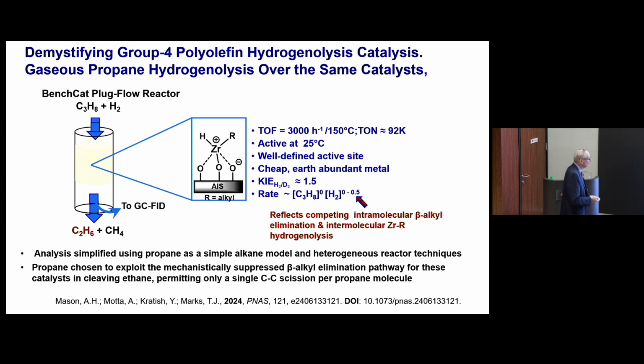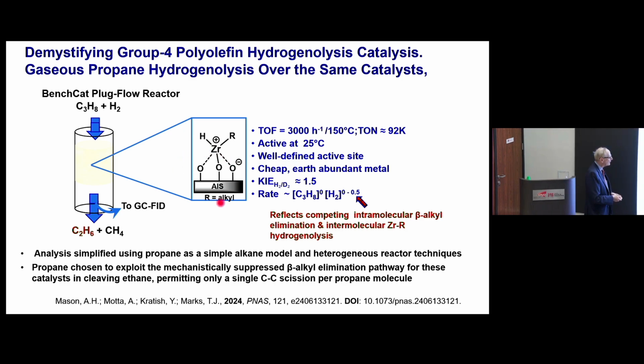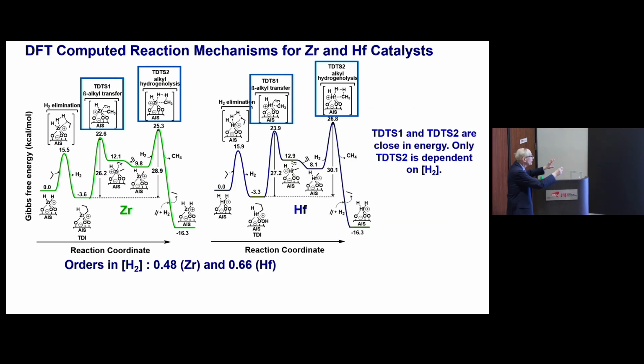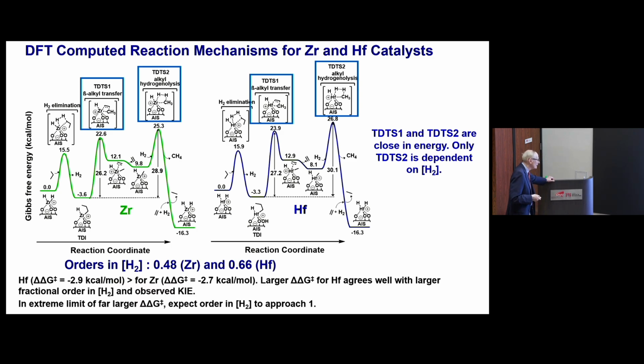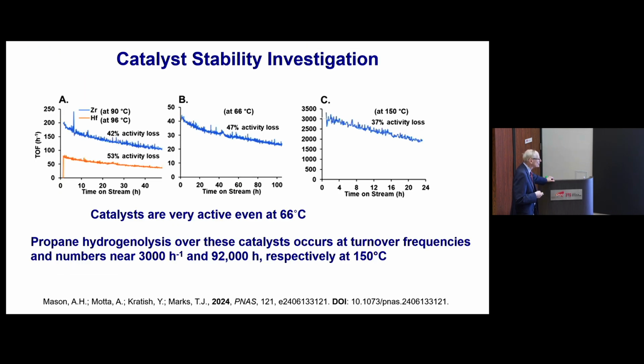And so, for example, the rate law is this weird thing that varies with the hydrogen pressure. And it turns out to be a very simple explanation. And I won't go through all of this. This is a lot to digest. But it's a competition between the beta alkyl elimination and the hydrogenolysis. And so that's why the rate law is fractional, depending on how much hydrogen you have. So we really understand this. And the calculation of the activation energies is very close to experimental.